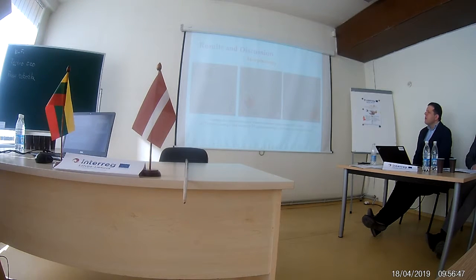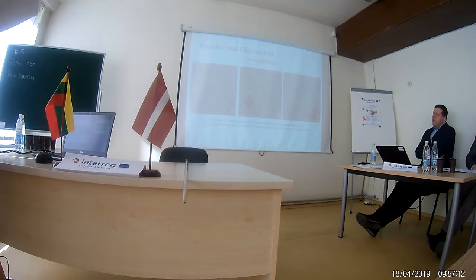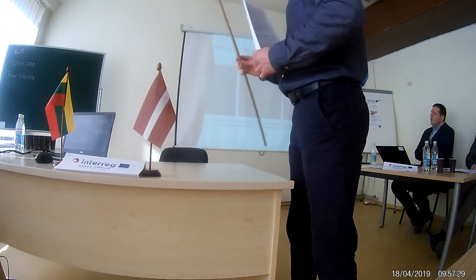The examination of microstructure of both coating groups showed a mixture of cellular and dendritic solidification grain structures. The mixture of grains in the clad zone was equiaxed, which corresponds to a homogeneous temperature field in all directions. In areas near the substrate, the microstructure has a larger proportion of columnar dendrites, which grow in the direction from the fusion line to the middle of the flattened beads.